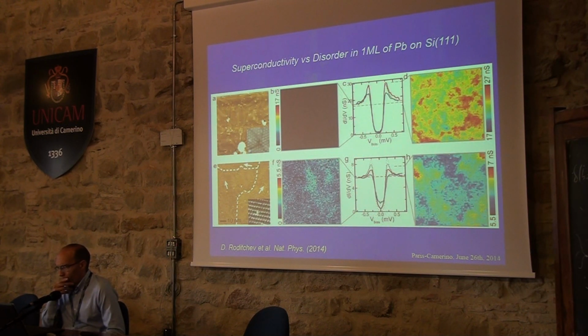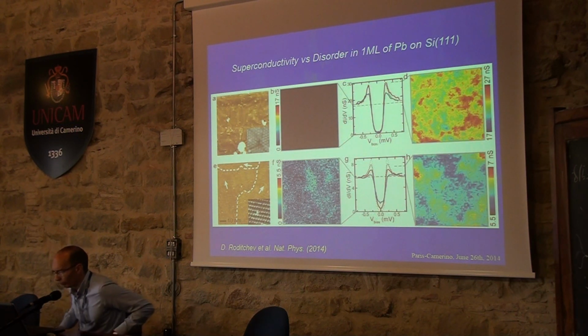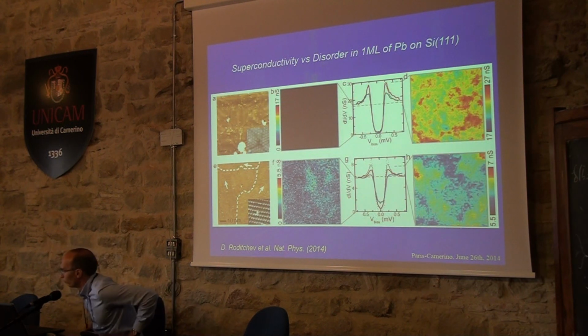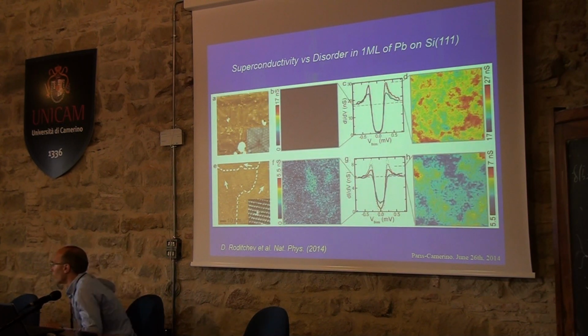You see that at zero bias conductance you have no states, and it is a completely, fully open superconducting gap. However, you have quasi-particle peaks that spatially vary, and this variation is represented on the top right map, in which high quasi-particle peaks are represented in red and low quasi-particle peaks in blue. And you see that there are spatial variations of those quasi-particle peaks, and the most striking effect is that this spatial variation takes place almost on the atomic scale, on a scale much lower than the coherence length. And this is quite surprising, because in superconductivity one doesn't expect such fluctuations to be present on a very short atomic scale.